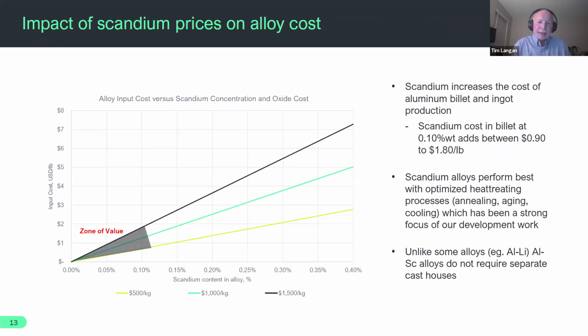So I mentioned some of the early work in the Soviet Union. They were using very high strength aluminum lithium alloys, and this is specific to the aerospace market. Lithium containing alloys are expensive on two levels. One is the lithium, it increases the cost. The other is you need to do very specific separate cast houses to make aluminum lithium alloys. The scandium addition can be used in any alloy, in any cast house. So we're not looking at a higher cost of manufacture. We're just looking at the cost associated with the scandium addition.